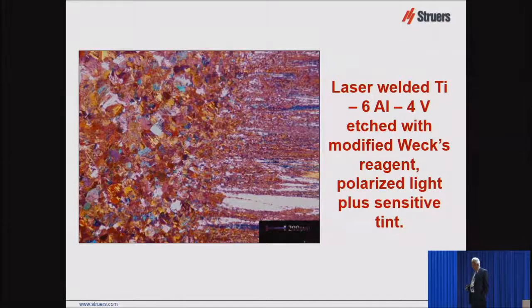And here's a laser weld in titanium, 6 aluminum, 4 vanadium, which is 50% at least of all titanium sold. And you can see the weld metal here, and over here we have the grain structure. And this is Erika Weck, she published the first color etch for titanium, 2% ammonium bifluoride in water. And I tried using that, but it was pretty weak. And then later on, she published the same thing, but with an addition of 50 milliliters of ethanol to it. And when I tried that, I wound up with white spots that were artifacts.